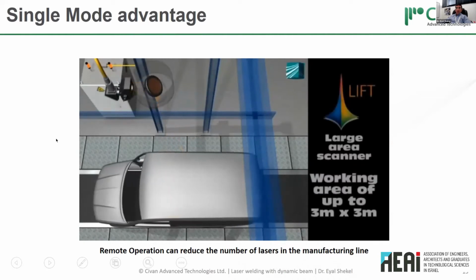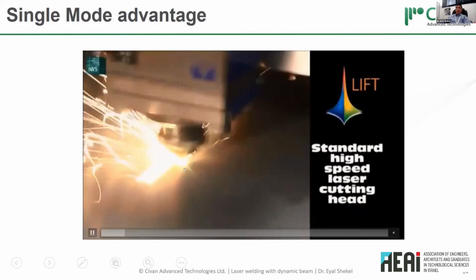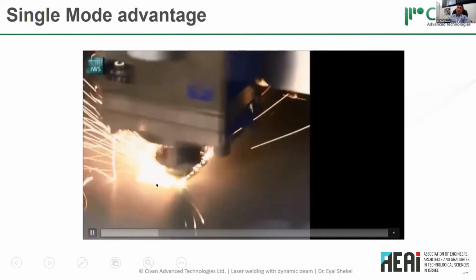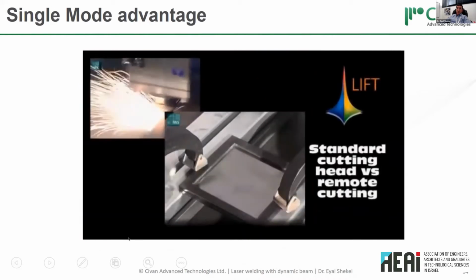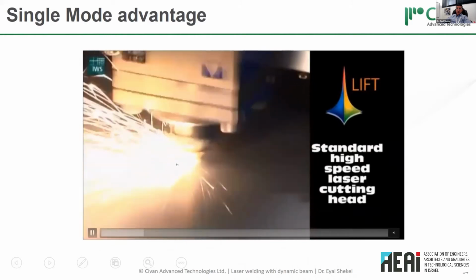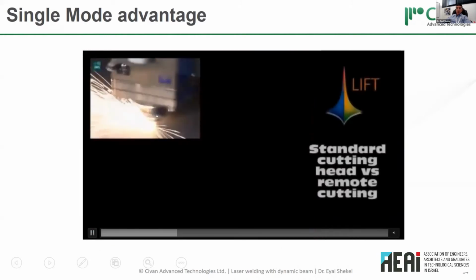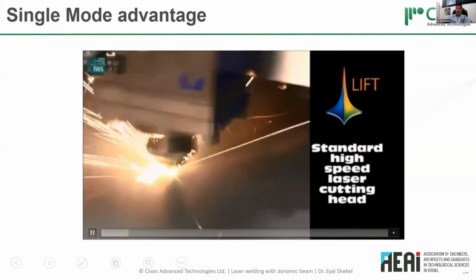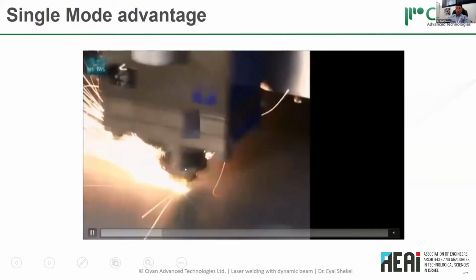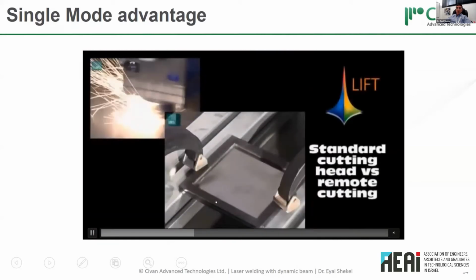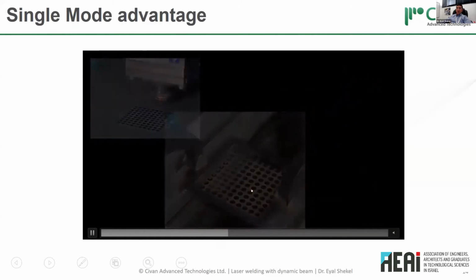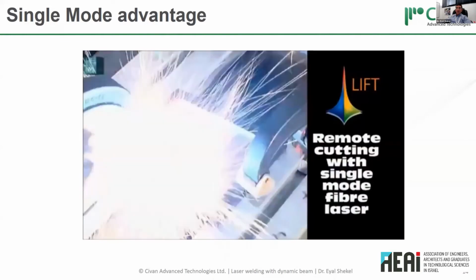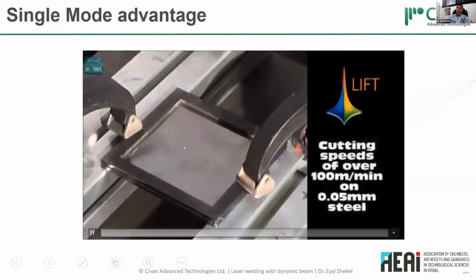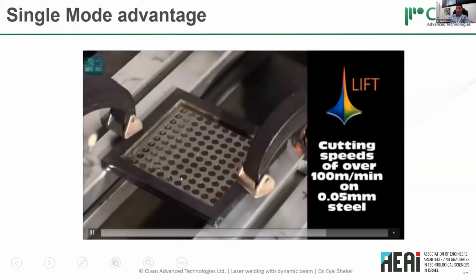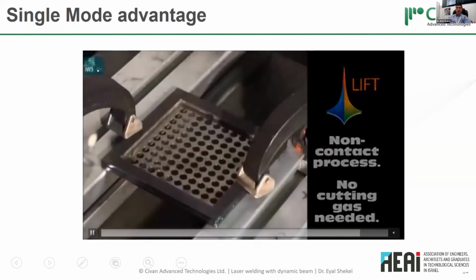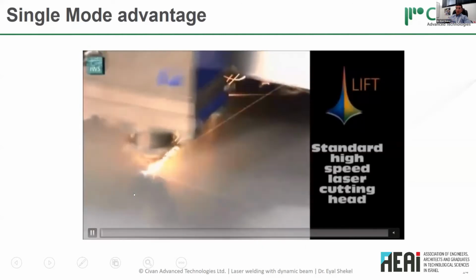Now, this remote operation has another advantage, and that is the speed. What we see here is a multi-mode laser cutting thin sheet metal. In order to do that, because the depth of focus is small, you have to work relatively close to the workpiece. And then the whole laser, the whole optical head, has to move in order to make the cut. Whereas in single mode, you can work from far, like we showed in the previous slide with a mirror. The mirror can move very, very fast, and you can see here remote cutting at 50 times the speed of the equivalent multi-mode cutting. This is courtesy of Fraunhofer IWS. This is done with a single mode laser.